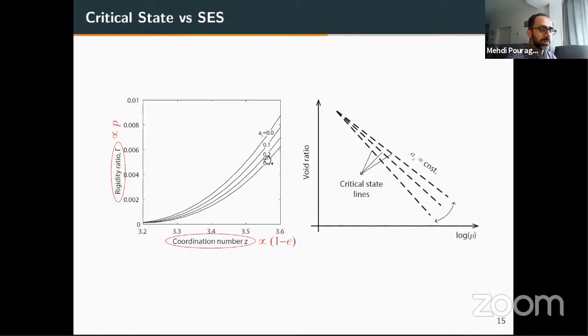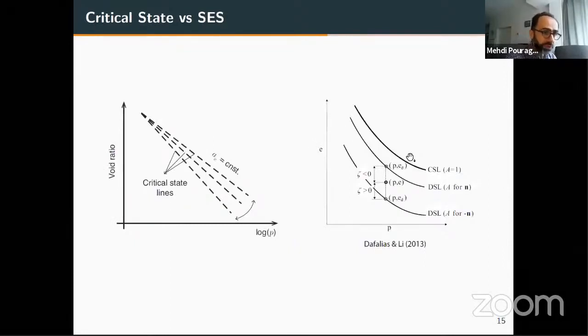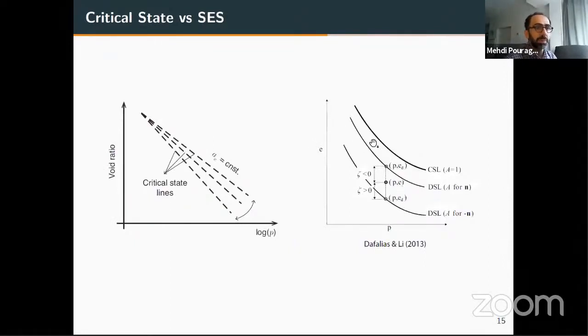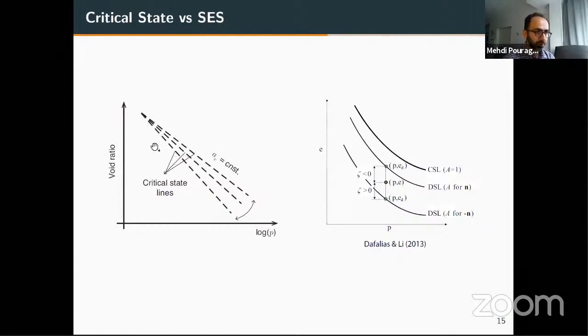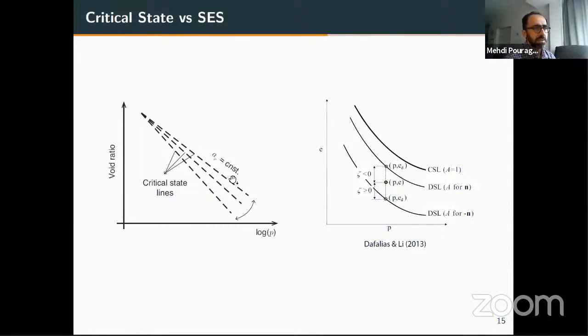So we see that the theory does not predict a unique critical state line, but it says that the critical state line actually depends on fabric anisotropy. And interestingly enough, this is what people have been trying to do. People have been trying to implement the effect of fabric anisotropy into the critical state theory in soil mechanics. And here we just get this naturally and organically out of the theory. So we do see how this idea of SES gives us a more generalized version of the critical state theory.